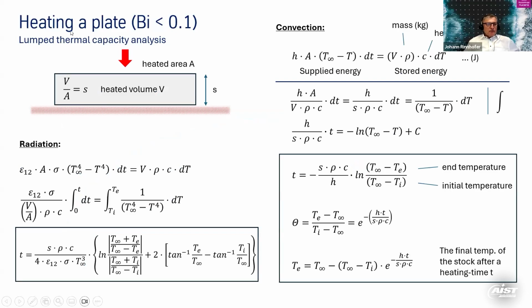When you heat a plate of thin thickness, that means you have no significant temperature differences in the stock. You say the supplied energy from the outside to this body is equal to the stored energy in this body. And then you go through this whole calculation, including an integration. You will end up with this logarithm here, and you can calculate the heating time. You see again this expression here for the temperatures. And you can calculate the final temperature of the stock after a heating time T, which is shown in here. We don't go into too much detail because that would cost too much time probably.